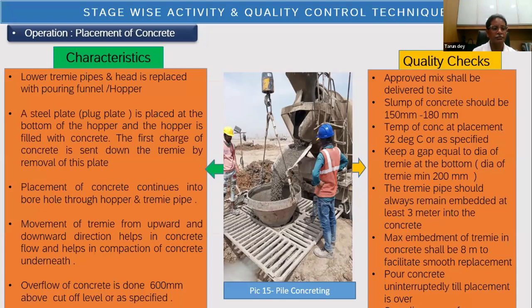Now, in this process, quite a few checks are there, which are extremely critical. First of all, the mix delivered at site must be an approved one, which should be verified through the document available with the concrete transporting equipment. Slump should be at least 150 mm, on the upper side 180 mm. This is recommended by the Indian standards. Preferably, I should say 180 to 200 would be preferable.